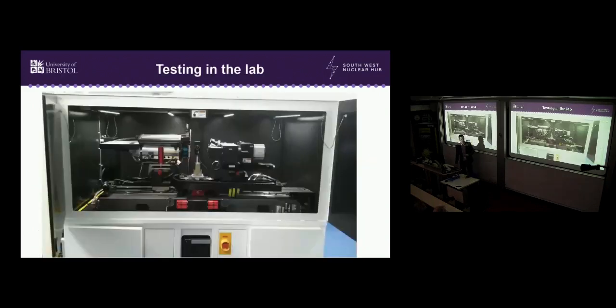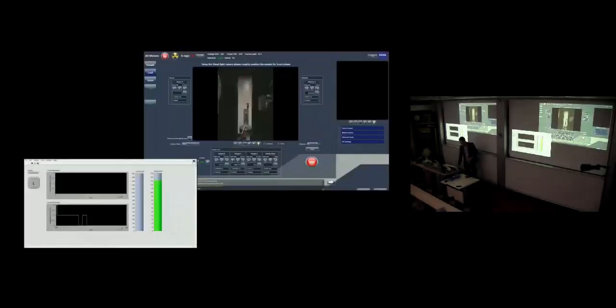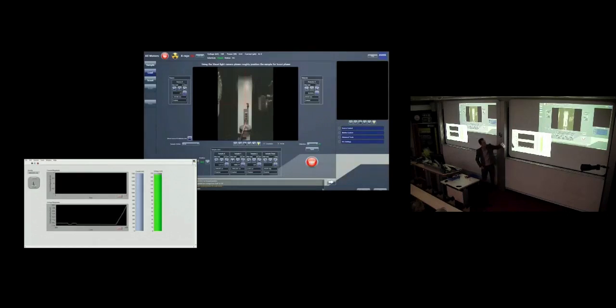Now, one of the ways we practice and test is with our lab XRT X-ray tomography system, which has quite a powerful X-ray generator. And we stick our gamma voltaic right in front of the X-ray generator. And what we do is we turn it on, and as we wind in the X-ray source so that it goes very, very close, if you look in the top right-hand corner, you can see the X-ray source being wound really close in. And you can see at the bottom here, this is the voltage that's being generated. Now we're getting up to 220, 240.